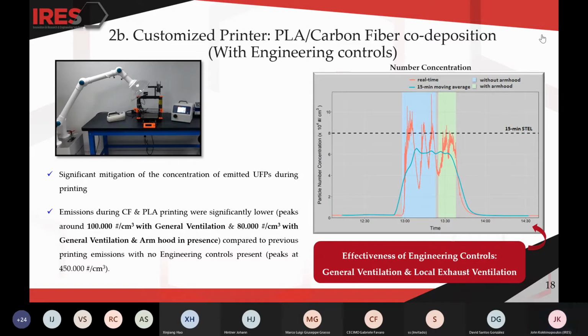So to sum up, given the previous slides' very high emission values, and for the purpose of emission removal and exposure mitigation, as we have said before, the experiment was repeated after applying general dilution ventilation with 10 air changes alone, and then general dilution ventilation in combination with local exhaust ventilation, the arm hood, as you have seen from the blue and green highlighted parts of the diagram. Concentrations during carbon fibers and PLA printing were significantly lower. As you can see, the peaks are at around 100,000 particles per cubic centimeter with general ventilation alone.